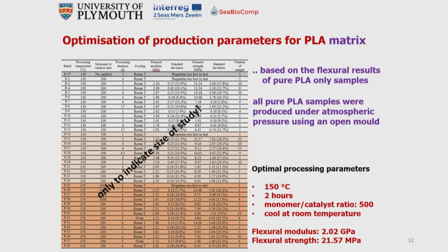Based on flexural results, all samples were produced under atmospheric pressure using an open mould for the PLA, because we can't infuse the PLA quite the same way as we can infuse the composite. We identified optimal processing parameters of 150 degrees centigrade for a couple of hours, monomer catalyst ratio 500 to 1, and cool to room temperature, and got properties that look reasonable, not special, for a polymer.